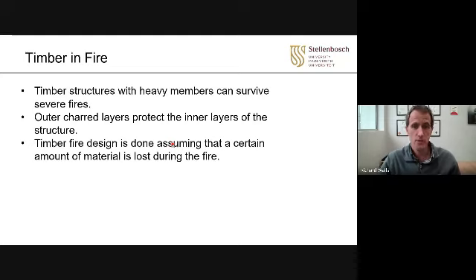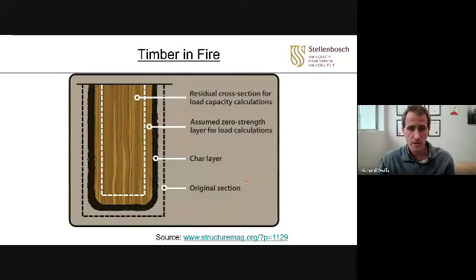Outer char layers protect the inner layers of the structure. Timber fire design is done assuming that a certain amount of material is lost during the fire. So this would be the basis. There is your original beam, the dotted black line, and the fire now occurs. And the material here gradually chars, slowly eats away. This will depend on the type of timber, but it may be between 0.6 millimeter and about 1 millimeter per minute.